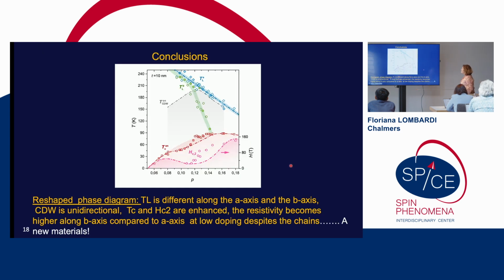You are essentially getting a completely different material. So the take-home message is that by nanostructuring the substrate, one gets a phase diagram that has been completely reshaped. You have the deviation from the linear behavior happening at a much lower temperature along the B-axis. You get an increase of TC and HC2. The charge density wave becomes unidirectional, and also the normal state, in terms of what you would expect for the resistivity of A and B, is changed at low doping, because B becomes much higher than A, so you have a completely new material. So what is next?